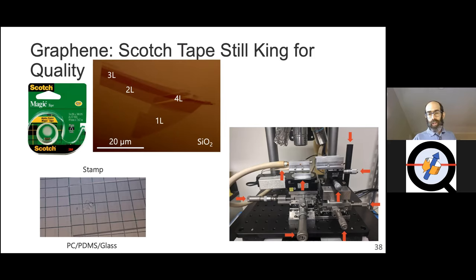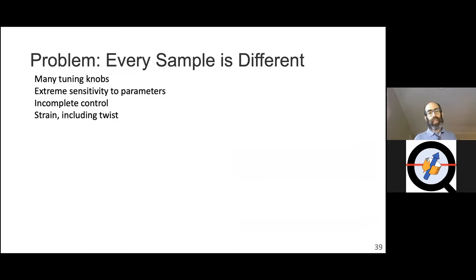So you can do great things with this kind of setup, but the problem is that every sample is different. There are many tuning knobs that we know about, the different twist angles. Everything's very sensitive, even down to 1/100th of a degree twist in some cases. We can't achieve exactly what we want in the sample, and there's strain that's important, including the twist that can vary across the sample. So though the superconductivity has now been robustly reproduced many times in Pablo's group and others, it's hard to get exactly the same situation in two samples.